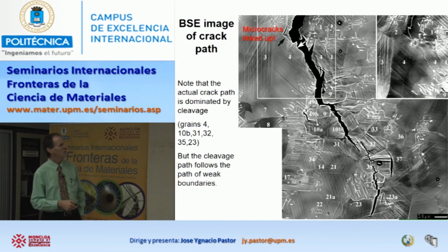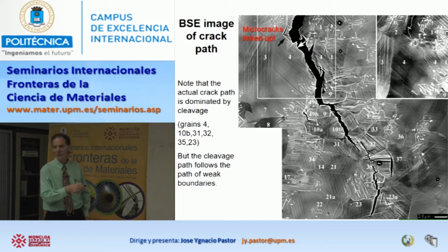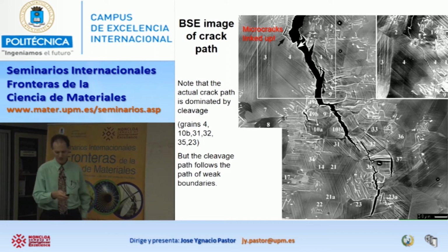So here's what really happened. Here's that grain boundary where all those little microcracks were. And they all linked together and made a crack. But sure enough, the crack made a major turn from the way that it was going and went in a different direction, in the direction of those weaker boundaries.